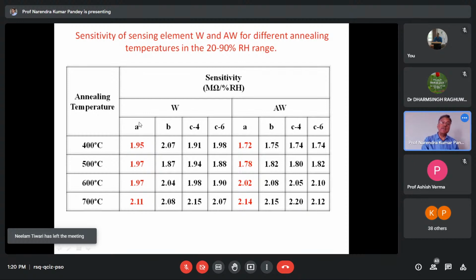This is when we are increasing the relative humidity. This is when we are decreasing the relative humidity. That is, we are seeing the hysteresis between the two. And this experiment has been done after 4 months. The sample has been tested, kept for 4 months, and the experiment repeated after 4 months. C6 is after 6 months.